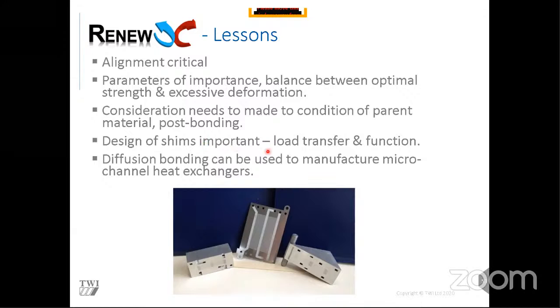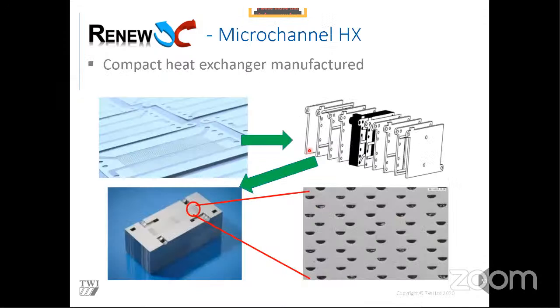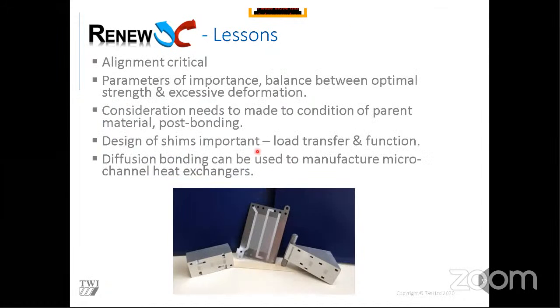The design of the shims themselves is important. In fact, I've not really discussed this yet. If I go back a slide, when we're applying the load, it has to go through each individual layer. And if you have any dead zones or dead regions, you will not get a bond. So if you've got a huge hole here, let's say, the layer underneath will not bond. So you need to really carefully design each layer to ensure that the load is transferred through the entire stack, to ensure that every layer is diffusion bonded well. So that's very important. In fact, I reckon for heat exchangers, shim design is the most important thing. You can play with the parameters, but the design is harder to change once you've made your parts. So here is the key part.